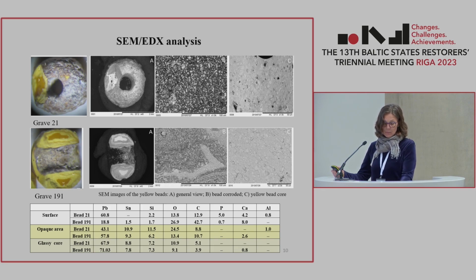In the corroded bead SEM image, B pictures, we can see lead tin oxide as white particles distributed in weathering lead-rich glass. Note the leaching of lead oxide from the glass due to weathering, which results in a lower average atomic number of the glass and hence a darker shade of gray in the image. We can describe the yellow bead core, same image, C pictures, as lead-rich glass, gray color, in which are lead tin oxide evenly distributed spherical grains of 2 to 5 micrometers. This observation we confirmed by elemental analysis in individual glass bead zones.